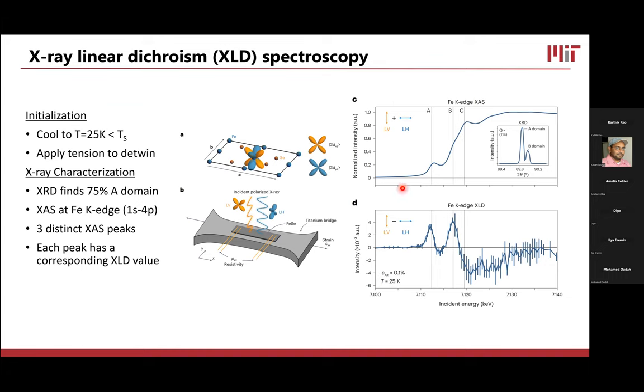So that gives us this top plot here. What we're doing is we're sending in X-rays that are linear vertical and linear horizontal polarized. And we move the incident energy of the X-rays through the iron K edge. And then we get an absorption step that looks like this. So we have no absorption below the edge and high absorption above it, with the corner basically being given by this feature B right here. So that's the usual center of the absorption edge.